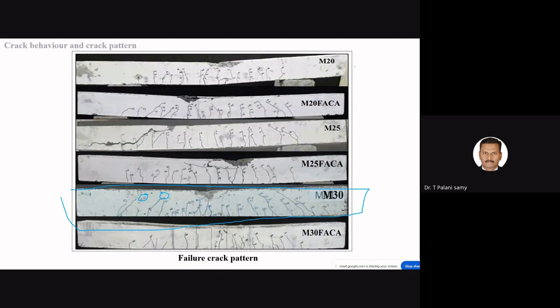Then, for example, first I want to compare M20 and M20 faca. The specimen is different, but the same length. You can see the pattern. Something is here, then something different in the pattern here. Then here the length is also different. The propagation of that crack also is different. So what we observed here is that we can count the number of cracks, and M20 has fewer than M20 faca. And you can measure the width of the crack also and the depth of the cracks, how much is inside. This also we can take into account.